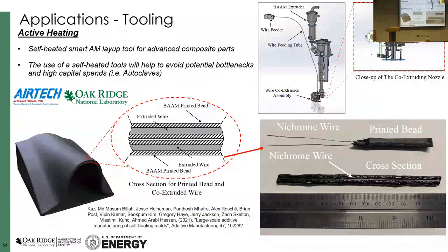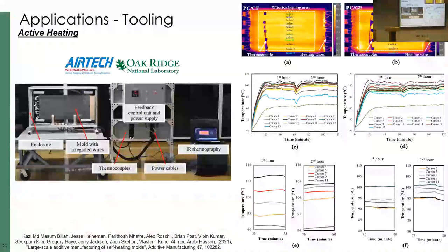So how can I move the heating elements? So we created a method that we can co-extrude wires during the 3D printing process itself, right? As you can see. So we co-extruded wire during the 3D printing process where we can just do Joule heating, right? So you can basically wire it up from both sides, send electricity, and then you heat up the entire tool. And we did it with some feedback control and stuff like that, and we managed to get less than about 5 degree difference on the heating surface, see, which is quite good, right?